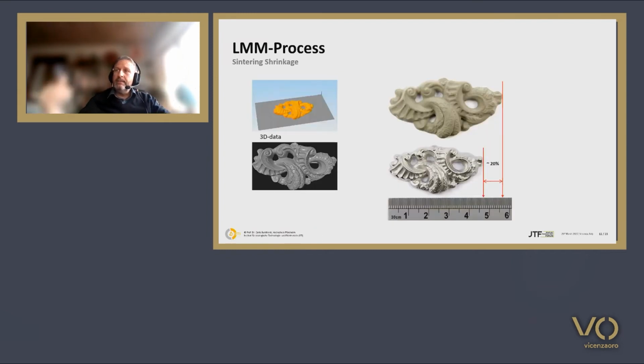So you have your 3D data, but because of the removal of this residual binder, you have a shrinkage. And this shrinkage I put down here with roughly 20%. Of course, we know it to the last digit, so 3 digits after the comma. We exactly know the shrinking factor, but this depends on the material used and the filling ratio. But for each feedstock composition, we know the exact shrinking ratio.